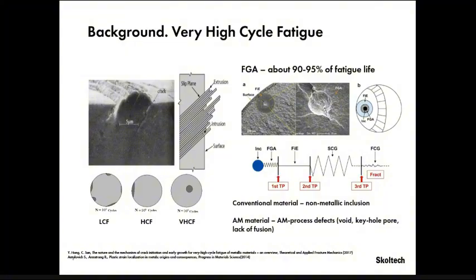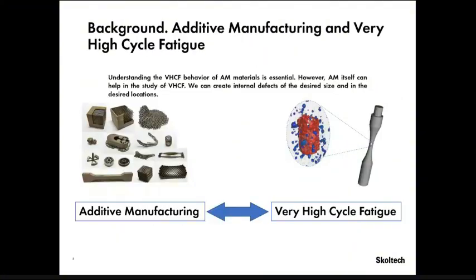As I said, the crack initiates in the bulk, usually from some internal defect. In the case of conventional materials, it's usually non-metallic inclusions. But for additively manufactured materials, it can be any process-induced defect, such as a pore or lack of fusion. The formation of the crack is accompanied by the formation of a fine granular area, FGA, which surrounds the internal defect. The mechanisms of its formation have been studied, but there is still no single model which describes it, and it's still under study. And it brings us to the idea of the work.